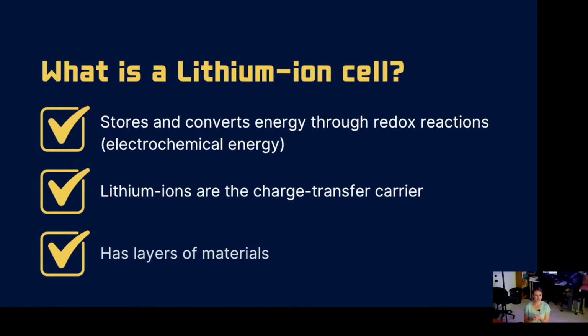How fast does the reaction work? How quick? Like how fast are they moving across the membrane? That's a good question. The question was, how fast do lithium ions move through the cell? I'll answer this more generally because I don't have the actual numbers of ion conductivity in front of me. But basically, the movement of lithium ions is really important because that determines the charge and discharge rate that's possible. You can change the speed of lithium ions through the battery if you change the charge and discharge rate. However, when you reach the maximum charge rate or the maximum discharge rate, there are certain processes that dictate how fast that's going to be, based on the slowest rate that the lithium can move through.